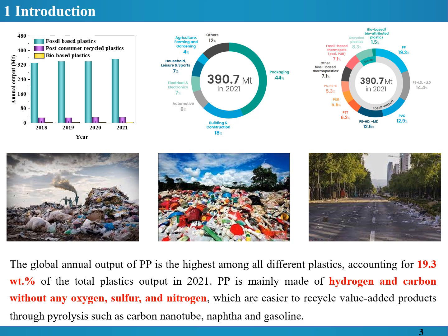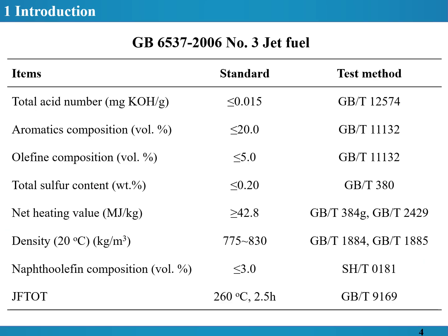PP is mainly made of hydrogen and carbon, without any oxygen, sulfur, or nitrogen, so it is easier to recycle into value-added products through pyrolysis, such as carbon nanotubes and gasoline. If the oil produced from the pyrolysis of plastics can be used as jet fuel, it not only alleviates the energy crisis, but also effectively reduces environmental pollution caused by waste plastics. This is a Chinese standard for jet fuel. This standard specifies that the aromatic hydrocarbon content of the jet fuel shall not exceed 20%, and the olefin content shall not exceed 5%.